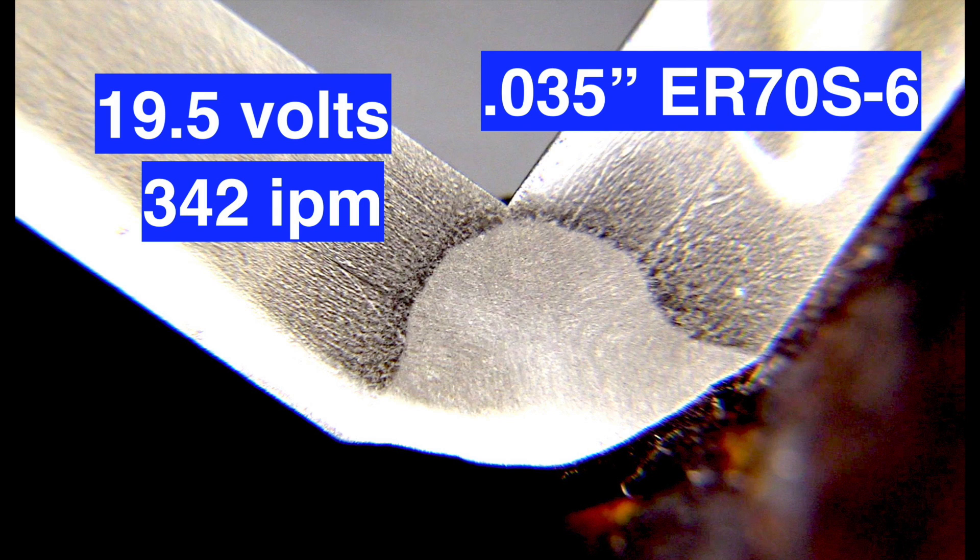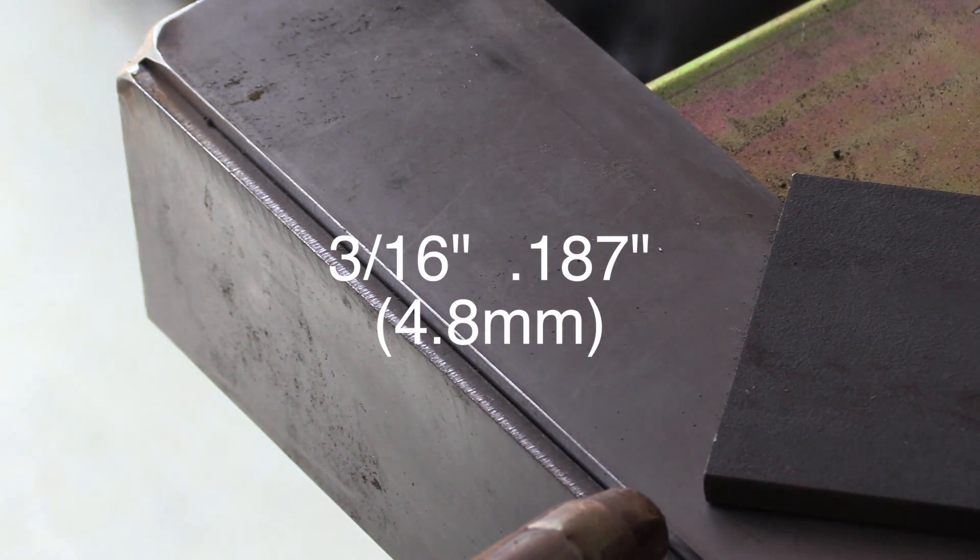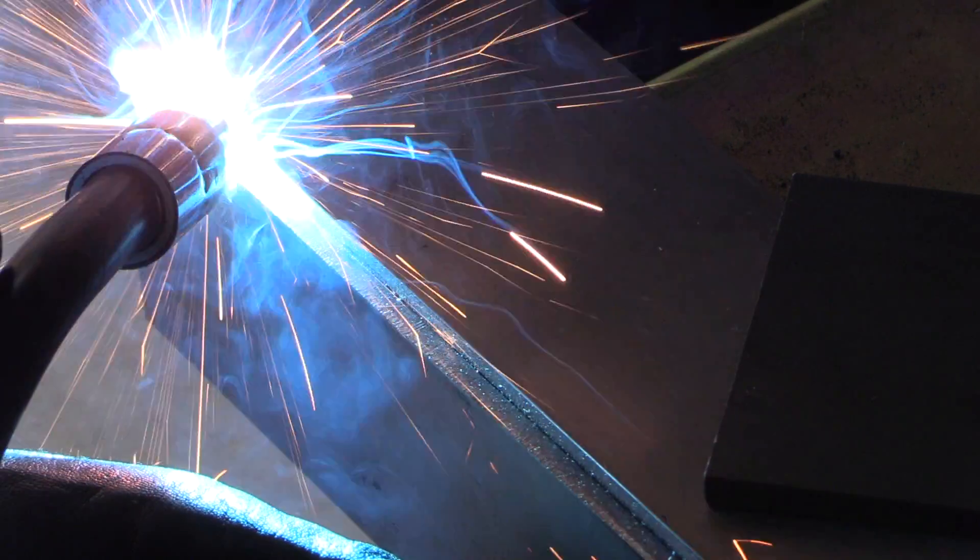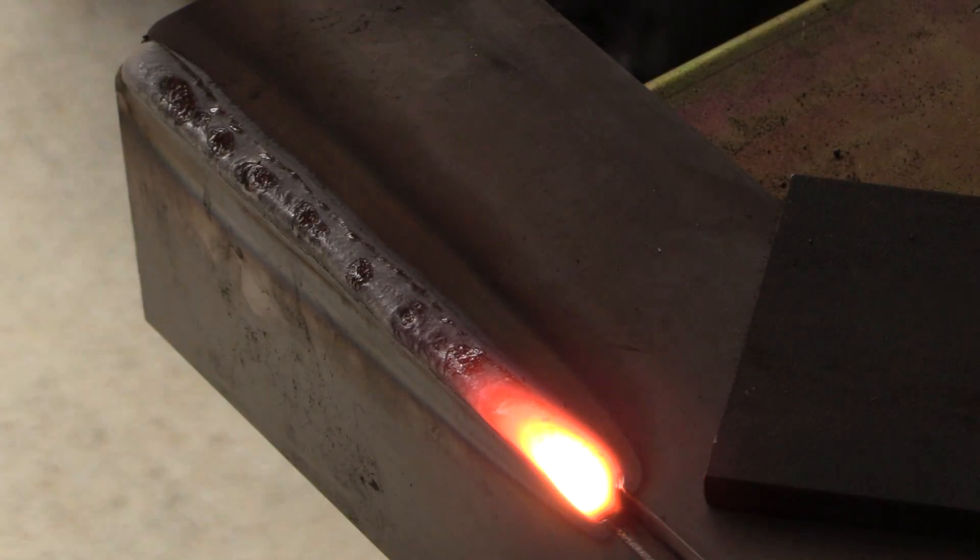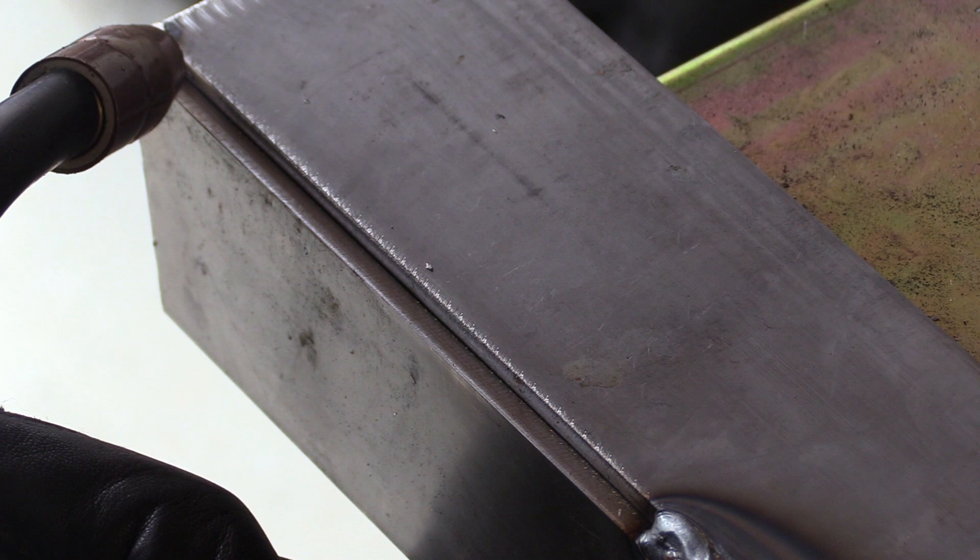Next I'm going to turn it over, just slightly change the position. Instead of welding flat, this is horizontal. There's really not much difference but for some reason it did change the way the puddle flowed a little bit. I'm using the stock settings here for 3/16 metal and I'm trying to go slow enough that I make sure to nip that top corner but not undercut it. Travel speed is maybe a little slower because I'm having to really watch for undercut whereas I didn't have to worry so much in the flat position.